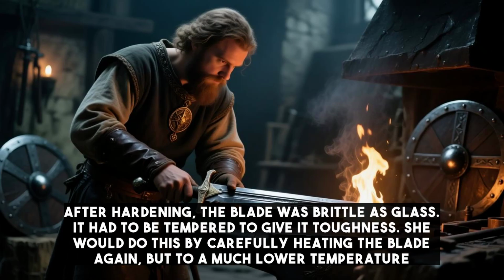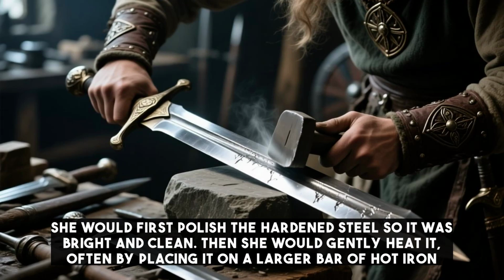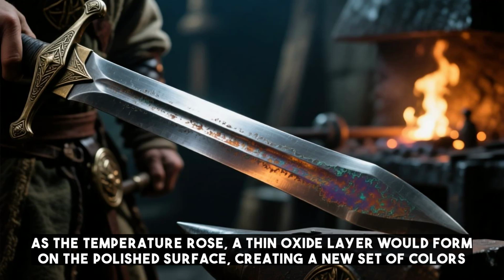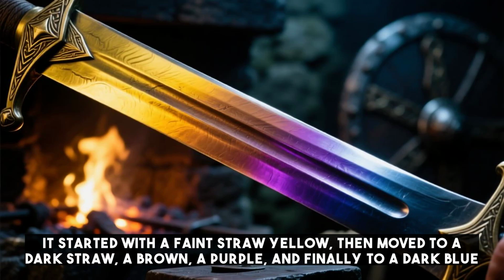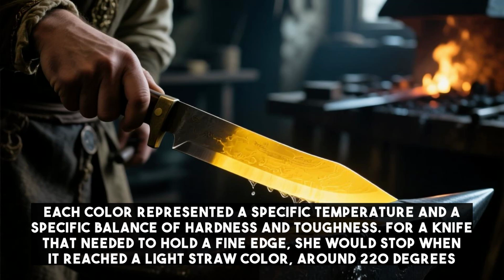After hardening, the blade was brittle as glass. It had to be tempered to give it toughness. She would do this by carefully heating the blade again, but to a much lower temperature. She would first polish the hardened steel so it was bright and clean. Then she would gently heat it, often by placing it on a larger bar of hot iron. As the temperature rose, a thin oxide layer would form on the polished surface, creating a new set of colors. It started with a faint straw yellow, then moved to a dark straw, a brown, a purple, and finally to a dark blue. Each color represented a specific temperature and a specific balance of hardness and toughness.